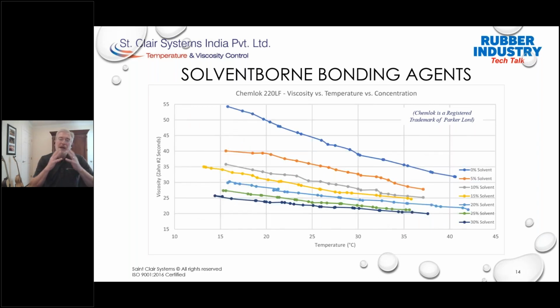Now, this same data sheet recommends that this coating be diluted with 25 to 50% xylene. And from this graph, we can see the viscosity versus temperature curves for various dilutions of Chemlok 220. Again, these were prepared by St. Clair Systems India in their lab and measured there.